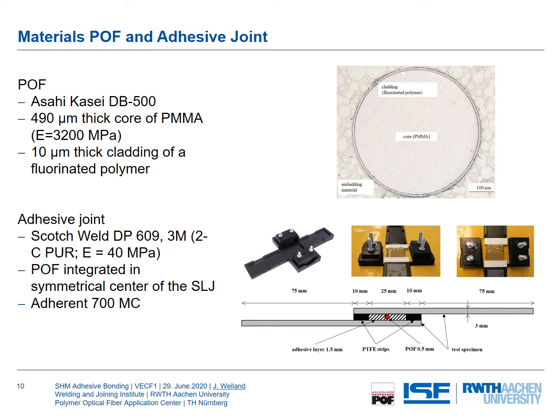Let's go a little bit more into the materials. POF, what does it mean? Polymer optical fiber. In our case, we use polymer optical fiber from Asahi Kasei, which has a diameter of 500 micrometers. That means the inner core, which is PMMA in that case, has a size of 490 micrometers, and the outer cladding, which is a fluorinated polymer, has a size of 10. Because of the different refractive index of these two materials, where PMMA's is higher than the cladding's, the light can go through it very well.